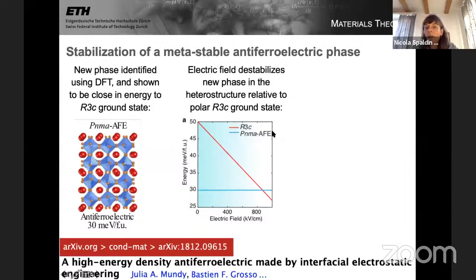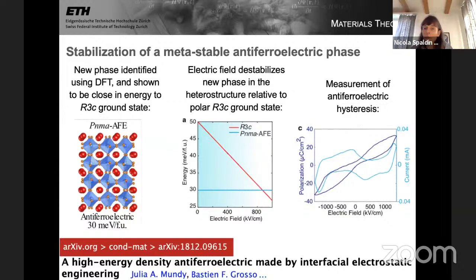Of course, the non-polar structure doesn't care about the electric field. It doesn't change its energy, but the R3C phase comes down in energy. And this is for a heterostructure, which is why the ground state, the polar state, is initially higher in energy because of the electrostatic boundary condition. And so let me show you the measurements then.